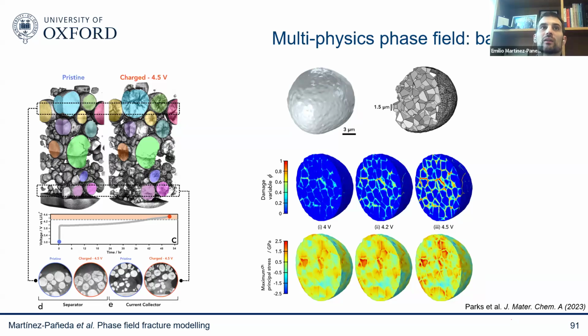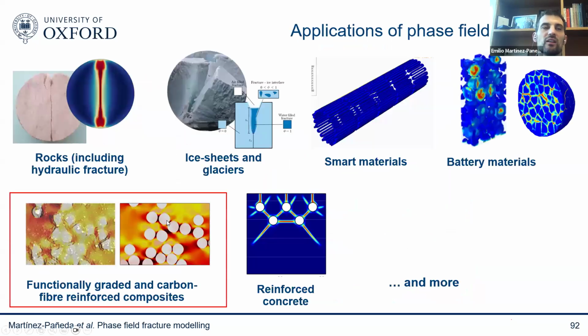And that allows us to answer critical questions that the industry is considering. For example, what if you make those particles of single crystals? What if you remove your grain boundaries? Or what if you make graded particles where the grain boundaries are bigger outside of the particle, smaller inside of the particle? All of those questions can be answered with those models that seem to be able to capture nicely what we see in experiments.